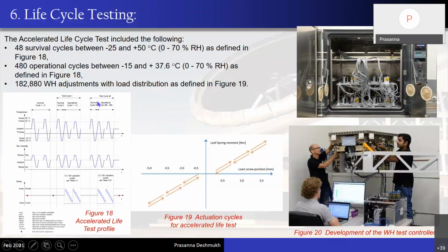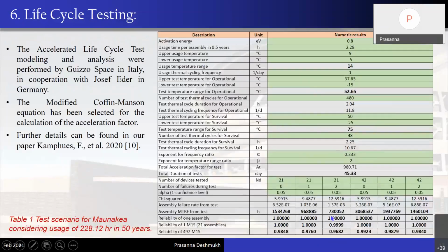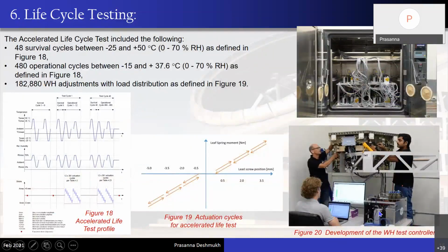So for conducting this particular testing, of course, we used the readily available environmental chambers, but for driving these actuators in the test cycles, we were required to use a specialized test controller, which is shown over here. This was developed in collaboration with TNO in Netherlands, and this is capable of reading and logging the data from strain gauges, and commanding the actuators in these predefined profiles.